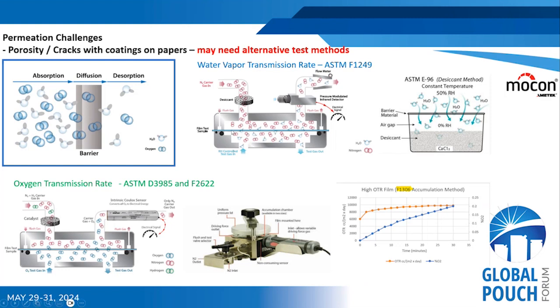However, if you've got a paper sample with a coating on it, but let's say the coating isn't great, maybe there are open areas, so now there's porosity of the paper that allows water to be pushed through, or cracks in the coating and the like, you could get erroneous results or very high transmission rate results with such a sample if it really isn't a nice, pristine, good coating on it.